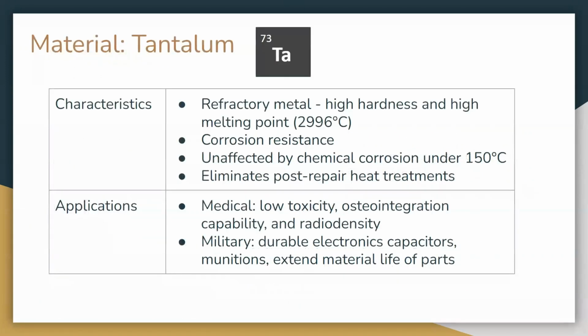So the material that I use in my research to spray as feedstock powder is tantalum, and a few general characteristics of tantalum. Tantalum is number 73 on the periodic table, and it is a refractory metal, which means it has high hardness and high melting point, which are great characteristics to have for a cold spray coating process. It also displays corrosion resistance, which will play a big part in the lifetime and durability of materials manufactured with tantalum. And also, tantalum is unaffected by chemical corrosion under 150 degrees Celsius. So, cold spray tantalum can also eliminate post-repair heat treatments because this can be costly and time-consuming.